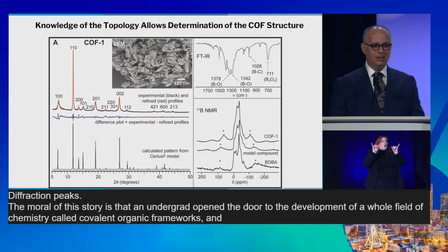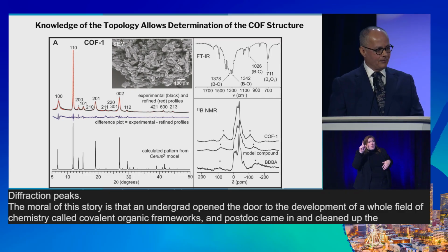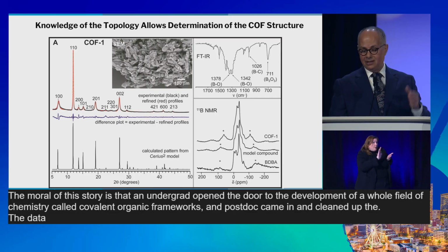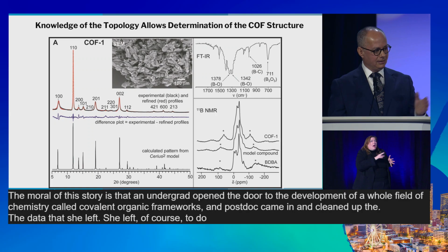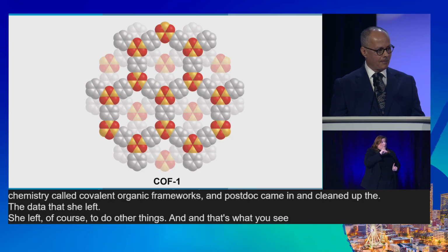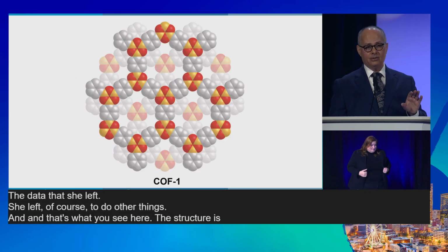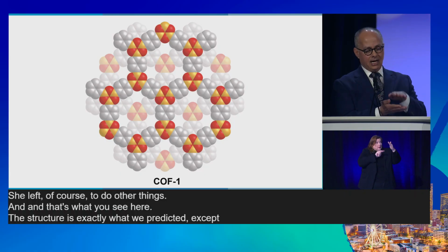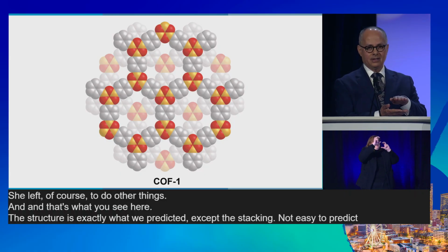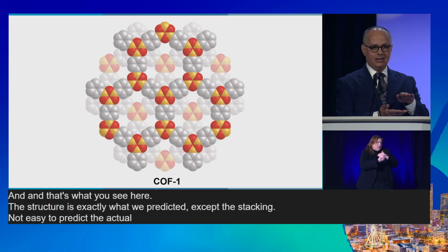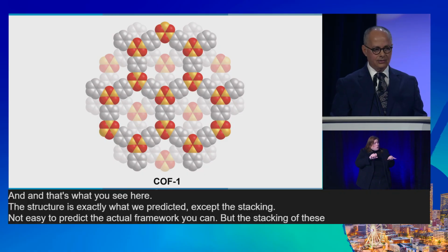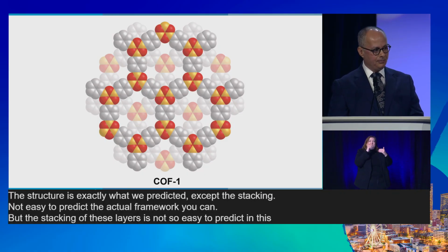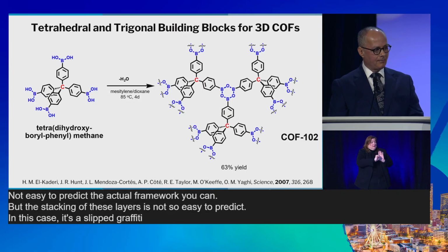And a postdoc came in and cleaned up the data that she left, of course, to do other things, and that's what you see here. The structure is exactly what we predicted, except the stacking, not easy to predict. The actual framework you can, but the stacking of these layers is not so easy to predict. In this case, it's a slipped graphitic layer.